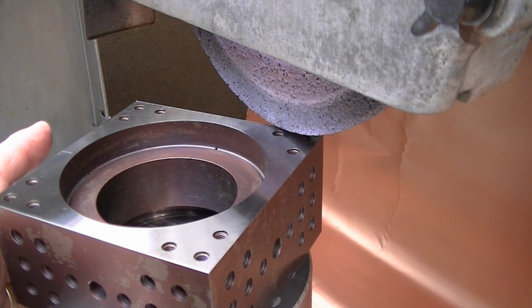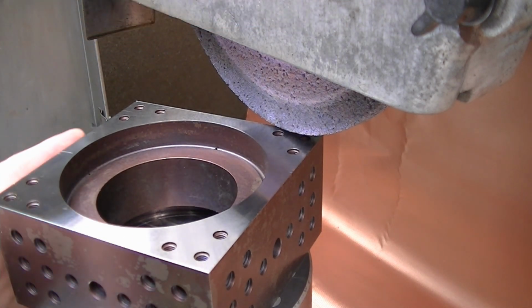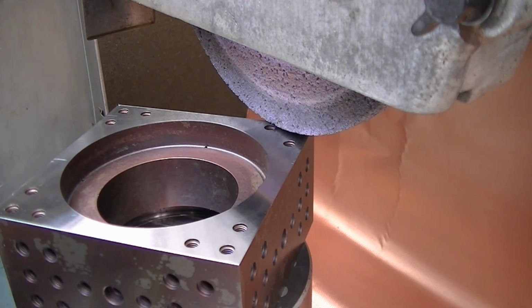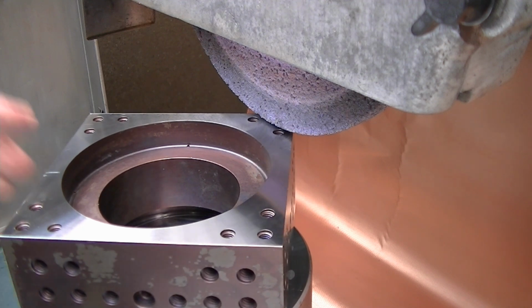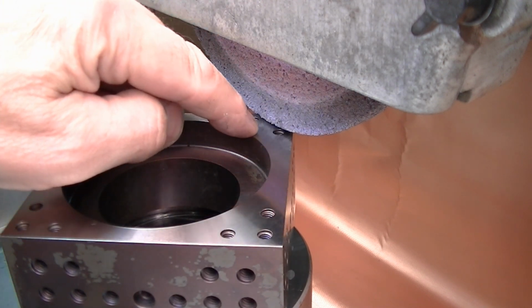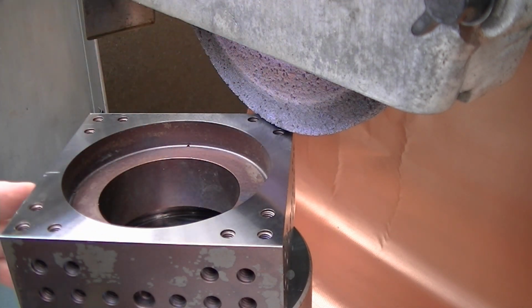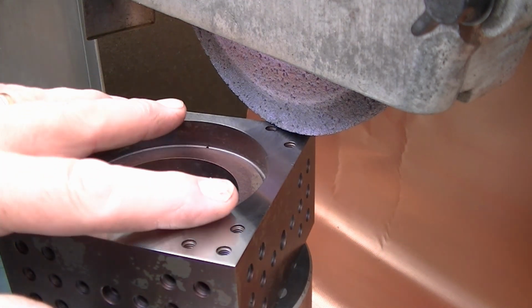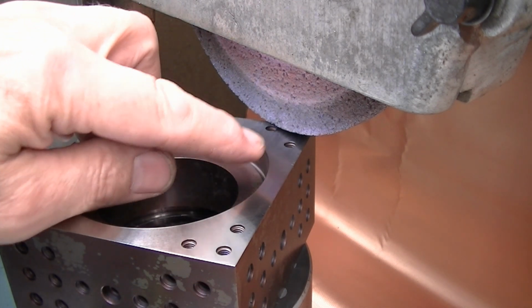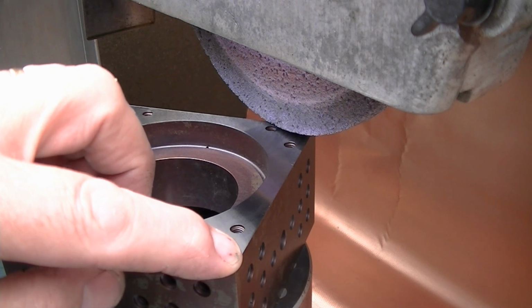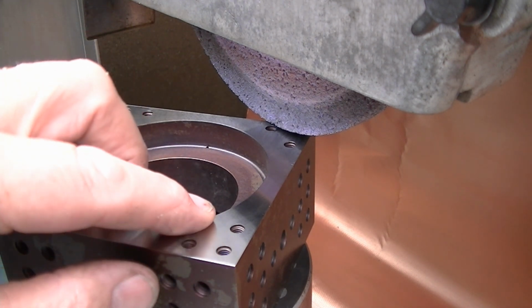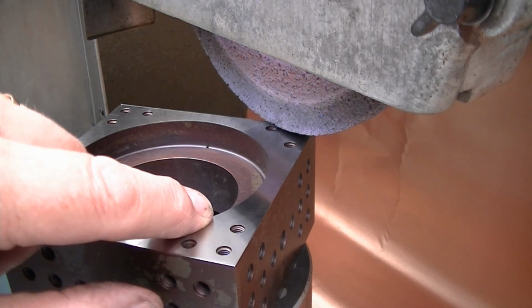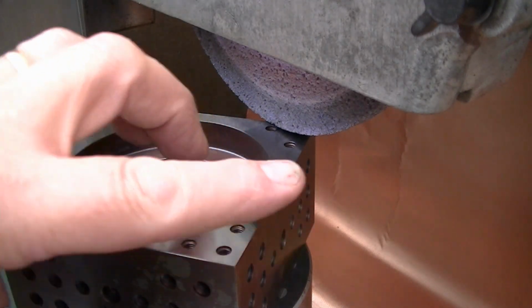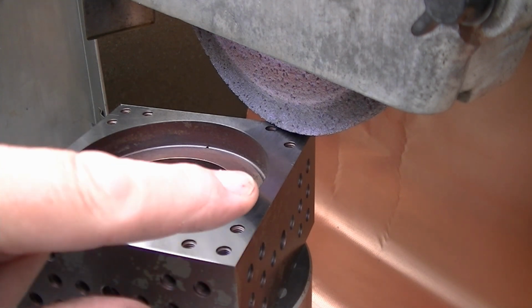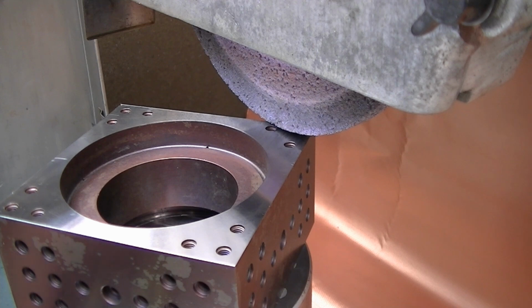But then when it comes here to grind up, there's mass to this whole system. And as it comes across here and the part tries to push the wheel up because of the resistance to grinding, it can't move that grinder spindle up as quickly as it needs to. It's going to actually be grinding lower here where it had to jump up than it is here where it was continuously loaded and just held up. So what you'll find is where you have the grinder tweaked in to be grinding perfectly flat, when you're doing your roughing passes and everything, this will be high here and low here. And if you're roughing and really barking the material off, as I did in some of these, you'll find this might be 5/10,000ths of an inch lower than here, just from this phenomenon of what I'm talking about here, where this is unloaded, loaded, and this impulse cut, where the wheel basically has to jump up on here because of the loading, causes it to grind deeper.